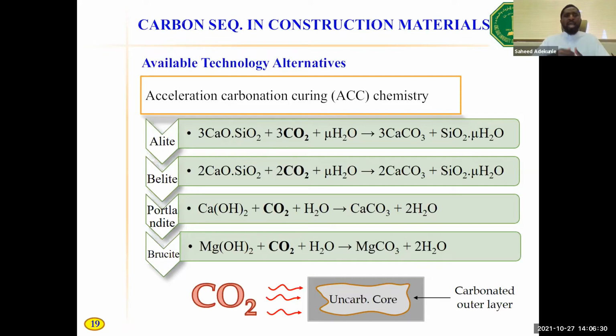And by the way, because we are doing ACC on young concrete, it is a mixture of unhydrated cement minerals, some hydrate of cement, and portlandite, which is calcium hydroxide. It's a young concrete. So you'll be having a mixture of unhydrated cement and hydrated cement. But the unhydrated components are the alite and belite that we're showing. They can combine with CO2 in the presence of water to form calcite. And most importantly, portlandite is a formation product of cement hydration. Portlandite can also combine with CO2 to form calcite. And some small brucite available in the hydrated cement can also combine with CO2 to form magnesite.